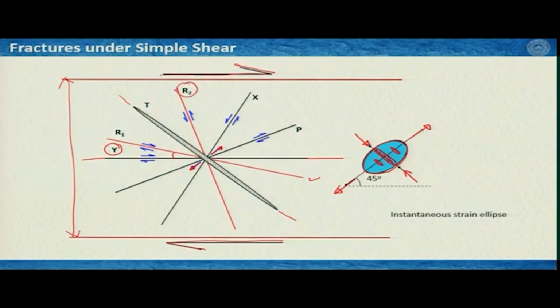You form another set of shear fractures which are known as R2 or high angle Riedel shear fractures. This angle is typically 75 degrees, and here interestingly the sense of shear is reversed. That means it is antithetic. So, the shear sense here is sinistral, but bulk shear is dextral. Some sort of mirror image of these two fractures form on the other side of the brittle shear zone. One is the P shear fracture, where the sense of displacement is synthetic, similar to the bulk shear direction, and then we have another set of shear fractures, X shear fractures, where the sense of shear is opposite to the bulk shear direction, or antithetic.